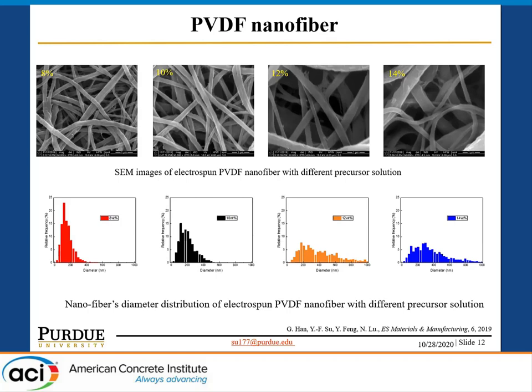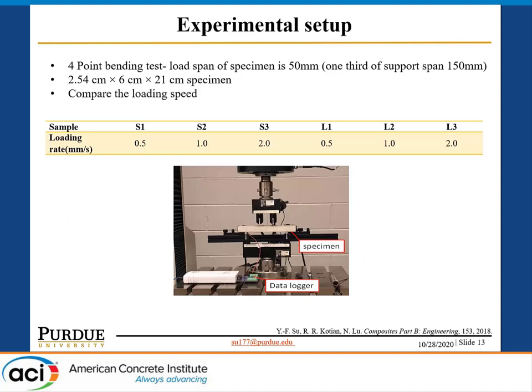Also, we did some pilot testing for the piezoelectric based energy generator, in which we embedded the PVDF nanofiber into the bendable concrete ECC. And then we did the four-point bending test. For the testing load rate, we varied it from 0.5 millimeter per second to 2 millimeter per second, and we had different lengths of the sample.